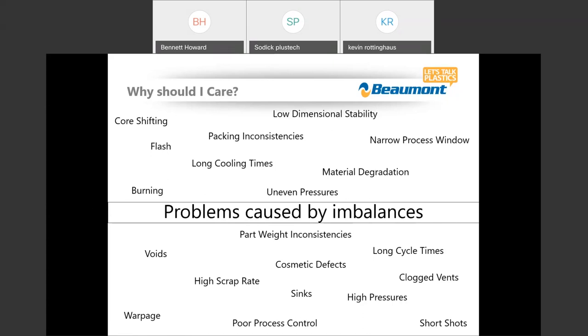We end up with higher system pressures as a result of this hydrostatic condition, where we have some cavities that are fully filled out while other ones are not. Poor process control. Nobody likes an imbalanced mold. Why? Because it leaves us with a narrower process window. If you had a choice of processing a single cavity tool versus a multi-cavity tool, everybody in the industry would go, well, I want the single cavity mold. Why? Because it doesn't necessarily have an imbalance from cavity to cavity.